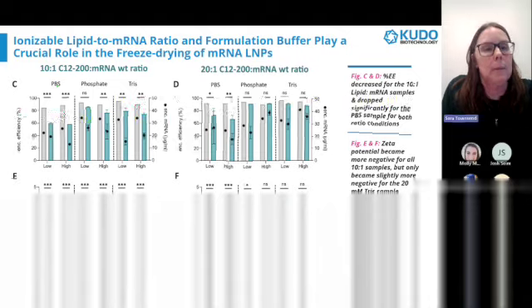So here is the zeta potential, as you can see, very negative for their PBS. And it's similar over here for 10-to-1. Their phosphate versus tris isn't performing that poorly, but the PBS performs much more poorly than the others.